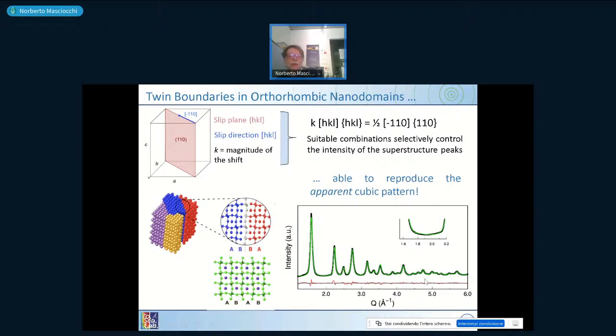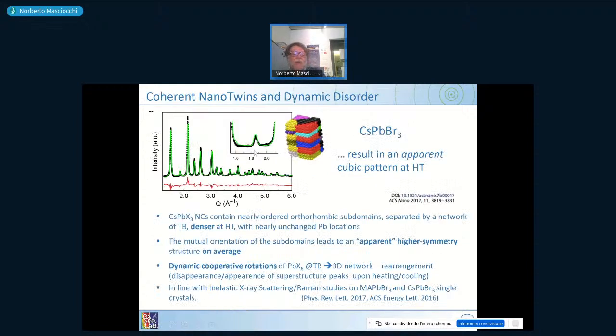appears to be cubic. So the idea behind that is that no cubic system exists, but in nano-sized materials you have domains of orthorhombic pieces which are hinged together in a very complex puzzle. Again, you can also have a different simulation. If you take a puzzle of this, these are all orthorhombic crystals, which would need to give many peaks here, and only one is given. It results in an apparently cubic system. So in nanomaterials, you have a continuous growth of symmetry, which is only apparent. It's always orthorhombic, but the mutual rotation of subdomains and the density of subdomains changes on changing temperature.